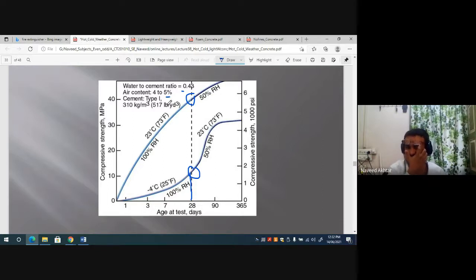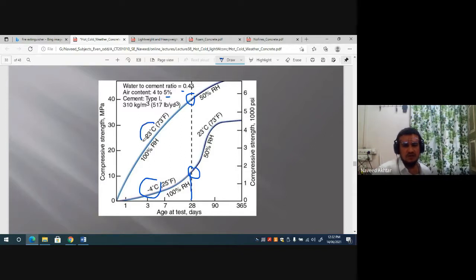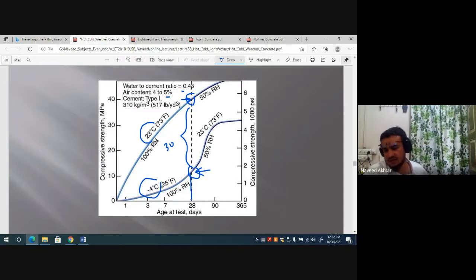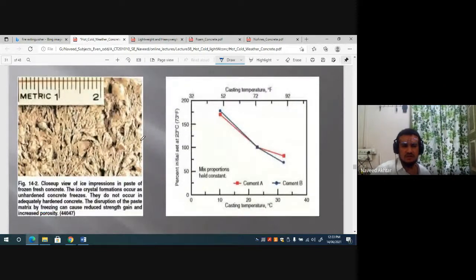Okay, but if the temperature is minus 4 degrees Celsius instead of 23 degrees Celsius, you can see the reduced strength. The strength of concrete at 28 days is much lower here, only about 10 MPa. Same concrete at 23 degrees Celsius has a strength of around 40 MPa. So you can see the very large difference, around 30 MPa, in 28 days strength, just because of the concreting condition in the colder region. Okay, so that is the problem.